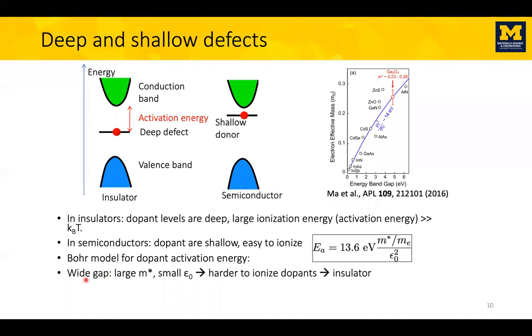But as the gap becomes wider, the effective mass, you see, becomes larger. This is a universal trend in materials: the wider the band gap, the heavier the effective mass. And it's almost a linear trend, as you see here. And also the material becomes a weaker dielectric, with a smaller dielectric constant. As a result, the activation energy becomes higher and higher as you widen the band gap, and eventually it's hard to ionize a dopant and you get an insulator.